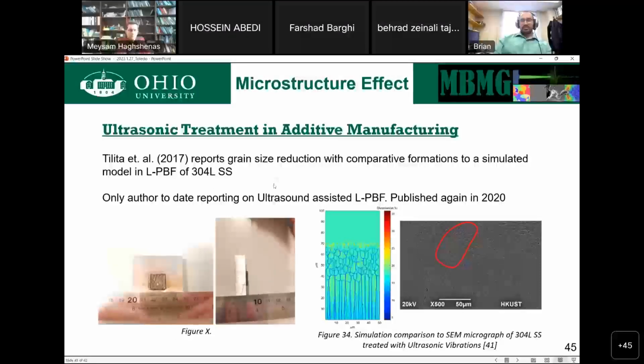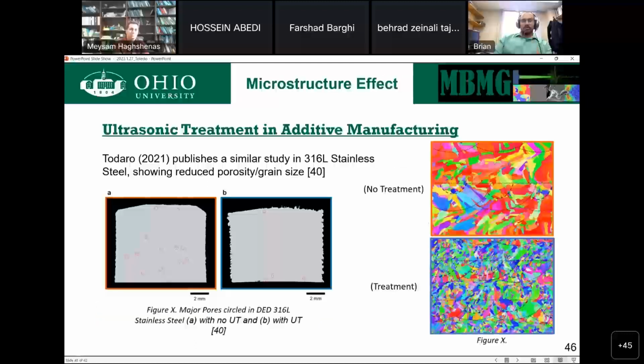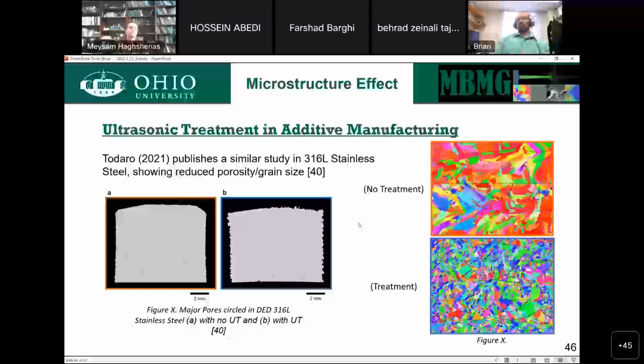There's evidence that suggests that you can do that in laser powder bed fusion as well in stainless steel. That was in 2020. Todaro in 2021 also again did this in stainless steel, looking again at porosity and grain size differences. So this has been shown to be feasible. Most of these studies do not use a full build plate. What they do is they take a transducer, create a sonotrode on top of it to increase the intensity of the ultrasound, and then build on top of the sonotrode. And that limits the size of the build you can produce.